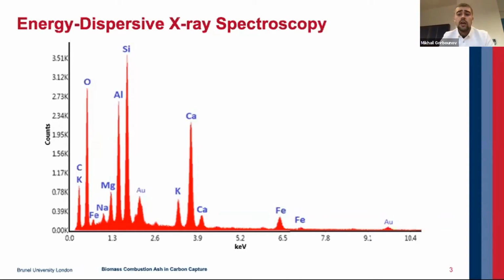Apart from that, we can also find potentially interesting compounds of elements such as alkali and alkali earth metals, such as potassium, sodium, magnesium, and calcium, with potassium and calcium being the most prevalent across all the conducted tests. As well, we have some iron and carbon. Also, trace amounts of phosphorus and sulfur have been identified on some of the scans, but the perhaps most confusing thing on the slide here is that we can see gold, but the SEM and the EDS are done within the same apparatus, and therefore that is the gold sputtering that I have just talked about.